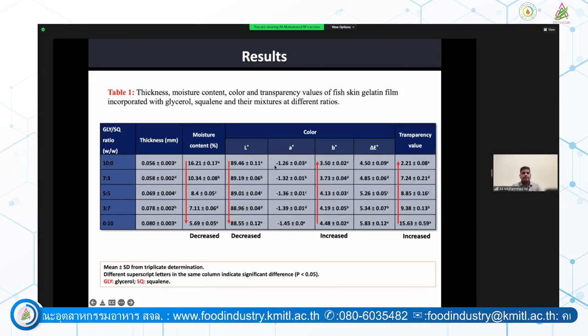And after casting the film, we found the thickness: the conventional glycerol film without squalene was thinner than the emulsified films. The highest concentration of squalene yielded the highest thickness of the film. And we could see that the moisture content of the film was significantly reduced by replacing the glycerol. So one of the hypotheses was correct.